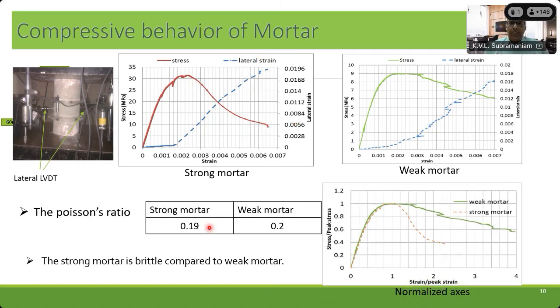Now, the Poisson's ratios of both of these mortars are almost equal, whether it is a strong mortar or the weak mortar. One is 0.19, the other is 0.2. So the Poisson's ratio is basically the lateral strain that is produced as you deform it in the vertical direction. Now, remember one thing, that Poisson's ratio is a property that is measured while the material is still linear elastic. So that's only valid up to about, say, 50% of the peak load. After that, when the material becomes nonlinear, we cannot have a Poisson's ratio measure.